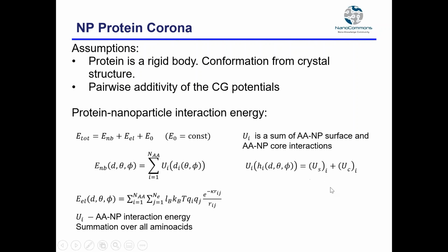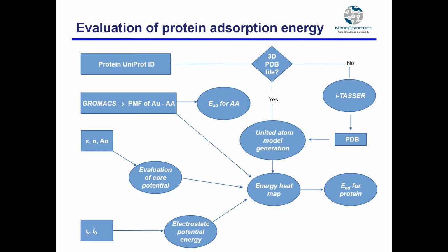So therefore, we calculate the surface interaction with a higher resolution and core interactions with a lower resolution, just by integrating the van der Waals forces over the volumes of these interacting elements. So this is the program. Now I'm going to show you the overall scheme.